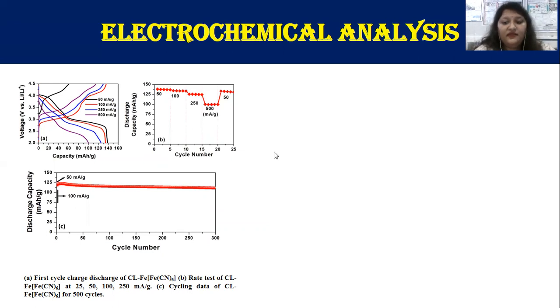So the discharge capacity of the lithiated Prussian blue analog electrode has been noted to be 138, 134, 125, and 100 mAh per gram at specific currents of 50, 100, 250, and 500. When the cell was cycled back to 50 specific current, it recovered a capacity of 133 mAh per gram. Apart from that, the cycling performance was also conducted, which is depicted in C. The initial capacity of the electrode was 118 mAh per gram, and this cell has maintained 92% retention at the end of 300 cycles, which is calculated from the third cycle.